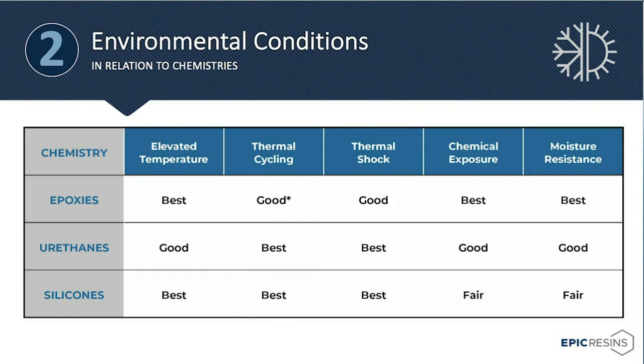When we look at thermal shock, epoxies, again, similar to thermal cycling, have the ability to have good thermal shock resistance. And this comes from prescribing the right epoxy for your application. When we're talking about urethanes, they really have one of the best abilities for thermal shock because when you're using a soft urethane, they have the ability to reduce the amount of stress on your components. Same thing with silicones in that regard.